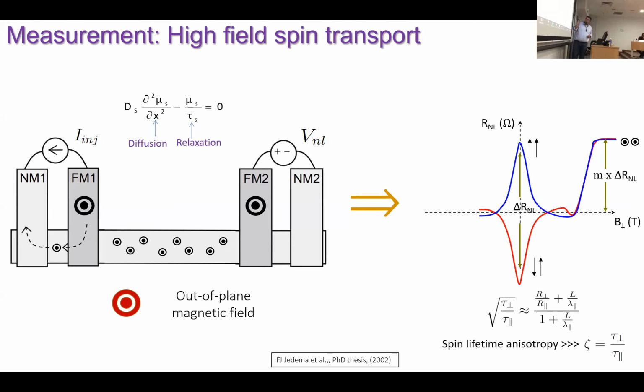So basically, this is the Hanle curve that I showed in the previous slide, where the spins were just pointing in plane. And here at high field, we start to force the polarization direction of the injector and detector to be out of plane, so that the spins this time propagating in the channel are out of plane. So by comparing the spin signal here and here, you will be able to get some information about something called spin anisotropy, like how the spin lifetimes compare along the in plane versus out of plane direction. I will be showing you how we use this to determine the spin anisotropy in black phosphorus later on.